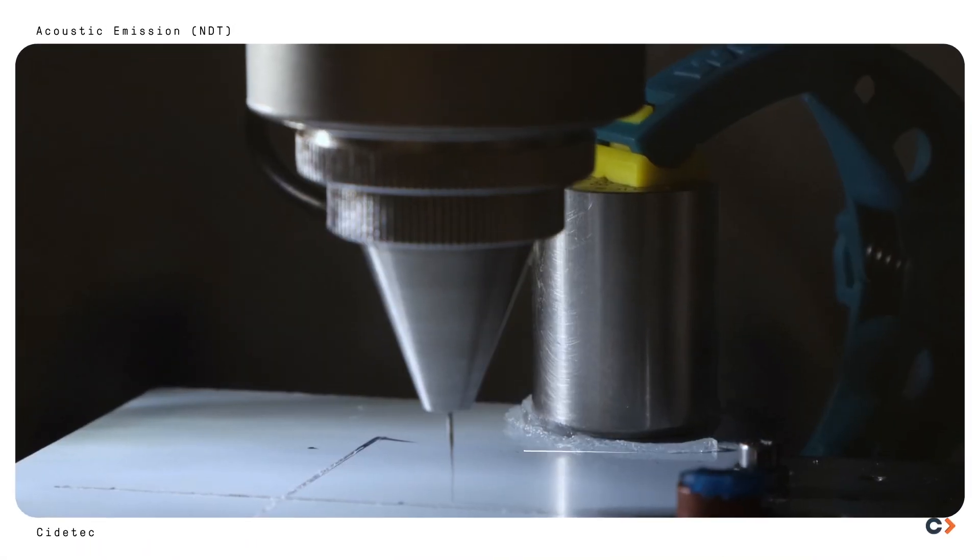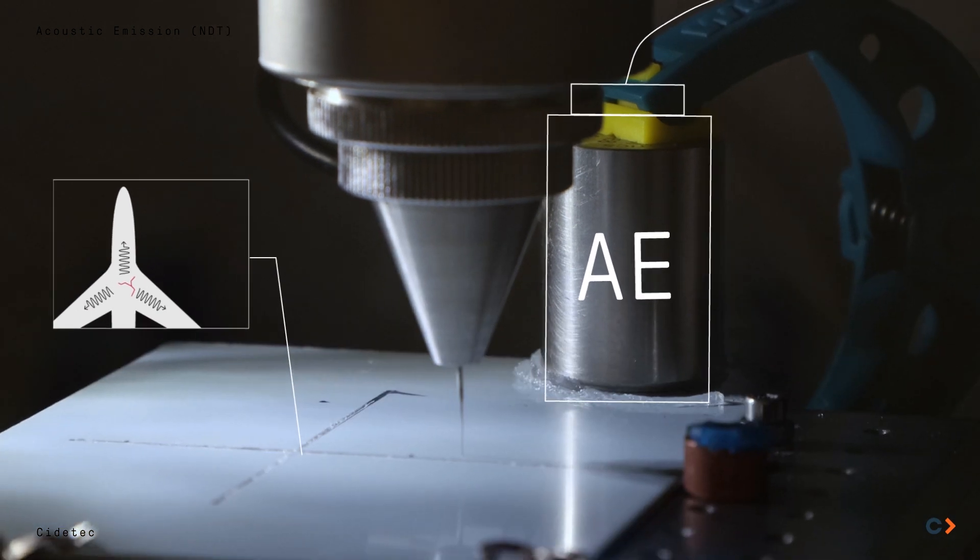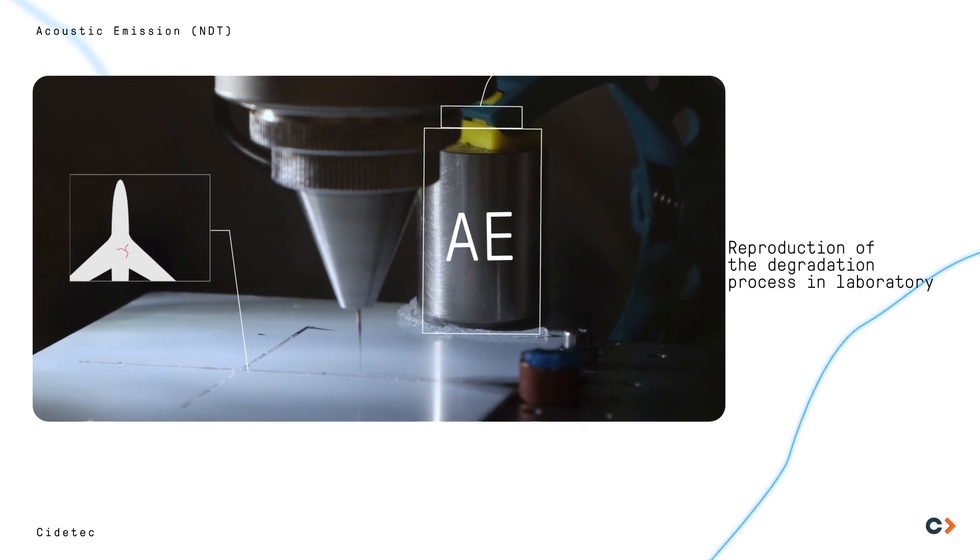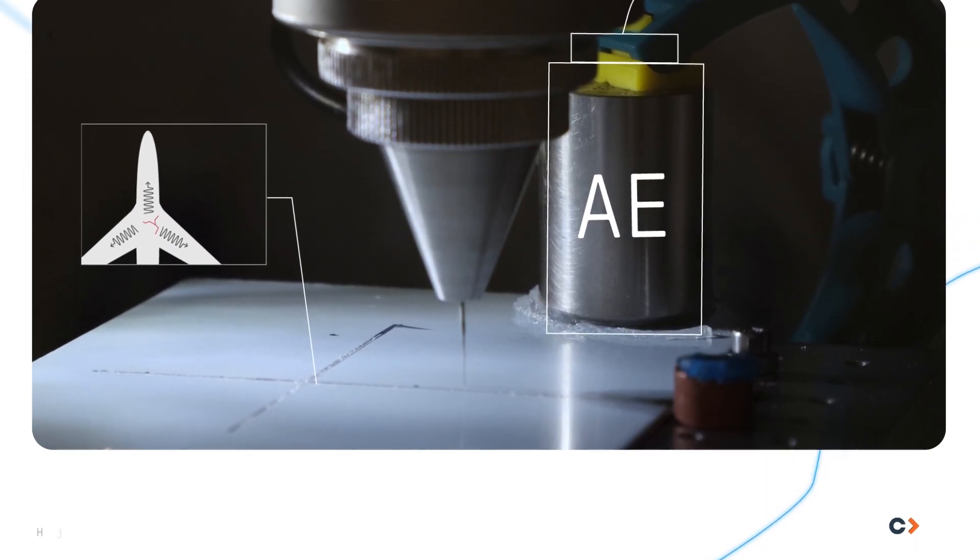So my job is, in one sentence, to find the characteristic waves coming from corrosion. But how to do that? In laboratory, we reproduce in a controlled way the corrosion phenomenon. In this way, we can track the growth of worms, that is, the progress of filiform corrosion.